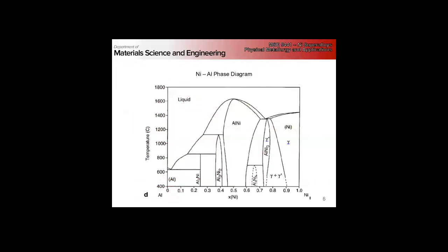If we look at about 80% or so nickel, we're in the two-phase gamma prime region, and we go up to quite high temperatures before we dissolve our gamma prime. We go full nickel in, we go full gamma above our solvus into a solid state regime before we start to see any melting.